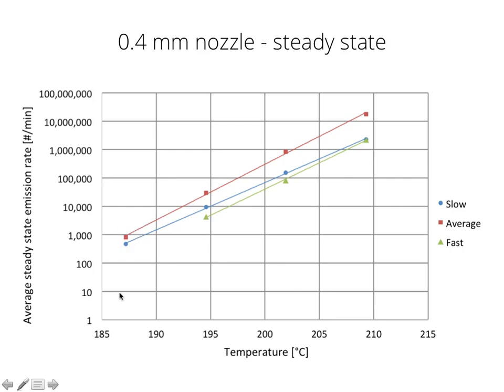And they show that if you actually print close to the melt temperature of, in this case, PLA, you emit very little particles. But once you increase your temperature just slightly, by target temperature by 10 degrees, actual nozzle temperature by 7 degrees, you can see there's a difference between 1,000 particles a minute to up to 17,000 particles a minute. And then if you increase the temperature further, it's an increase from 17,000 close to 1 million. And then once you're at 1 million, you can already reach 17 million. So a few degrees Celsius make a difference between a few thousand particles and millions of particles.